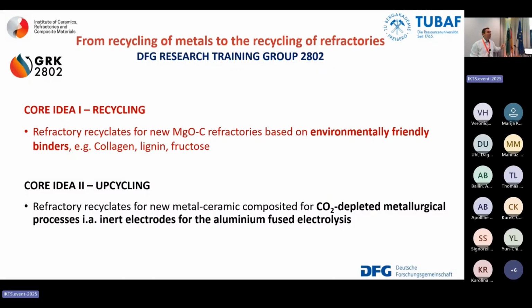And the next idea was, okay, let's pick up the MgO-C, make MgO, and make a marriage with steel. We have made in the past, also in another center, metal matrix composites. We have taken zirconia and we have taken a TRIP steel, and we have made a composite system and we increased the strength and the elongation of the steel via the zirconia destabilization in situ. And then we said, okay, if we can do this, let's pick up magnesia, pick up steel, make again the marriage. Why? Because I wanted to create carbon-free, inert electrodes. They are not inert, they are also reacting, for the aluminum electrolysis. So get rid of CF4. Get rid of CO2.